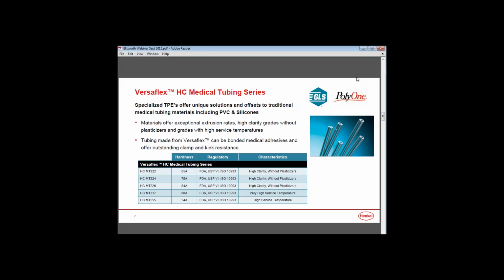All of them are certified for USP Class VI and ISO 10993-4 and 5. Very, very low extractability profiles. A lot of that is because they're using no plasticizers at all. Although we didn't do the testing, we have multiple applications in the market that also meet 10993-10. And these materials, depending on the application, are sterilizable by most techniques. In the event of gamma and E-beam, depending on the color shift requirements, there may be a need for some colorant additions to not affect the aesthetics of the materials.